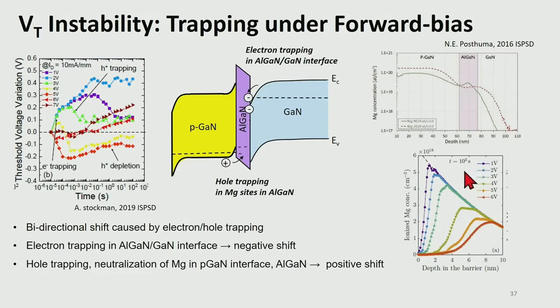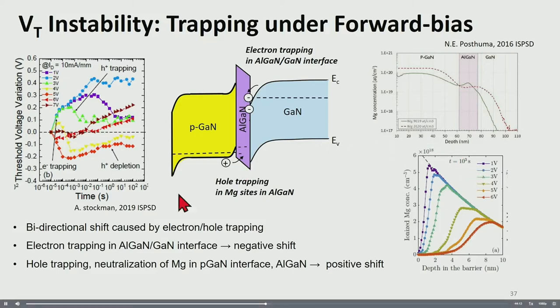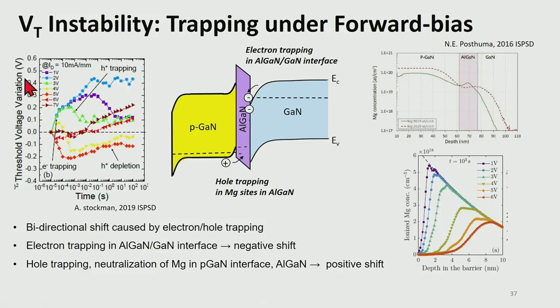In addition to the pure dynamic effect, there is also trap-induced VT shift. So this left figure monitors the threshold voltage as a function of stress time under different gate voltage conditions. When gate voltage is relatively low, we typically observe the negative VT shift, which is due to the electron trapping at the AlGaN-GaN interface. But if you increase the gate voltage further, we start to see the positive VT shift due to the hole trapping or the neutralization of magnesium dopants.